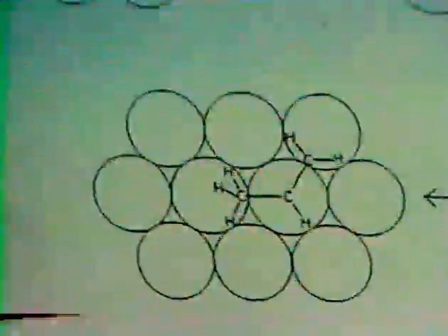We had originally thought, because when we did the isomerization of this molecule, we did not get much deuterium in, that this kind of isomerization was forbidden. And so we postulated this 1,3 over-the-top kind of isomerization. It turns out that when we labeled the molecule with deuterium, in fact, what we found was that the hydrogen migrates over the bottom to give us isomerization, and when we use deuterium, hydrogen still migrates across the bottom.